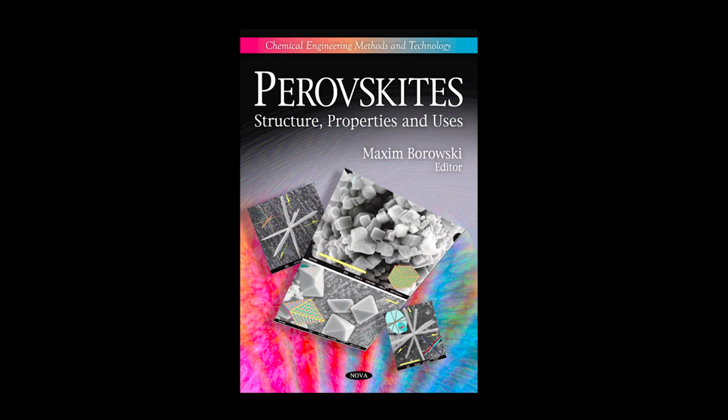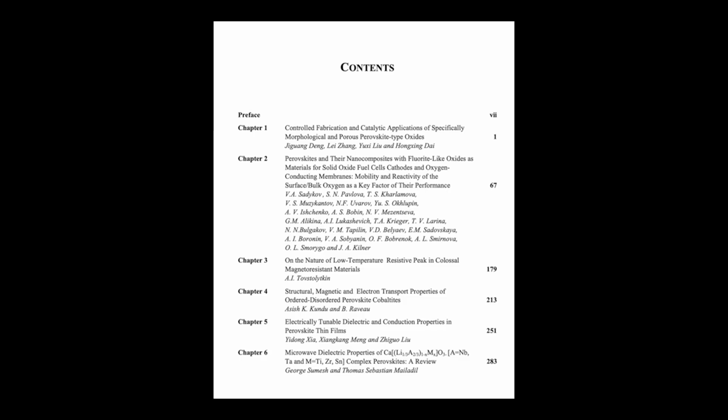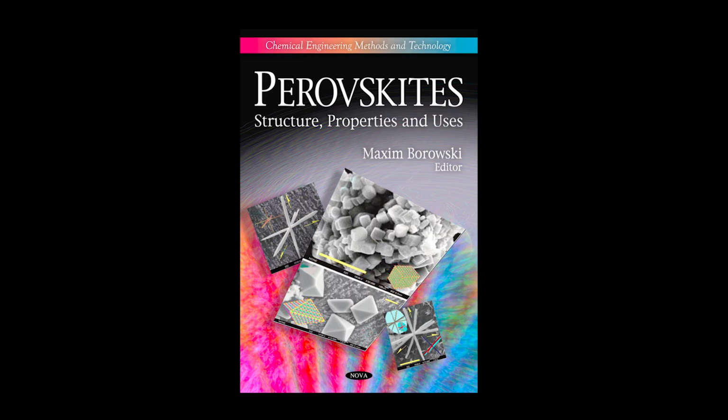Yeah, the main challenge, especially when you're working with lanthanide-based perovskites, is the thermal instability of the metal salts, often used as precursors, things like metal nitrates or acetates. The temperature you need to completely burn off the polymer template, which is typically around 500 to 600 degrees Celsius, is often high enough to cause these metal salts to melt or decompose too quickly or react aggressively before the perovskite structure has properly formed and solidified. If that happens, the ordered macropore structure collapses. The walls break down, the pores fuse. You just end up with a disordered chunk of material, completely destroying the inverse opal architecture you worked so hard to build. It's a common problem.